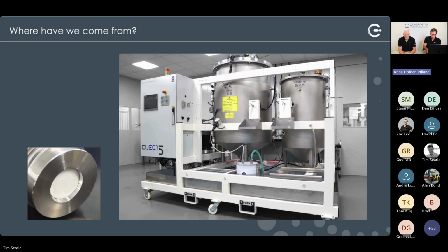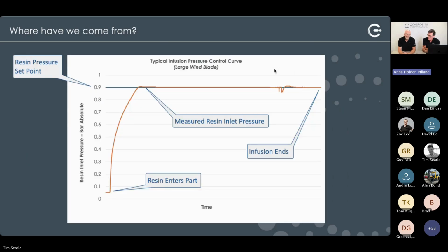And part of that journey was evolving the next generation of meter mix equipment, designed not just to mix and dispense materials, but to condition them carefully prior to the infusion, to infuse them directly into the tool with no intermediate stages, to get rid of buckets and hundreds of pipes, and to have extremely accurate control over pressure, flow rate, ratio, temperature, all whilst being able to feed on demand at fully variable flow rates ranging from almost zero right up to, for example, 30 kilos per minute. So verification and data collection really evolved during this sort of 2000s, 2010, 2020 period, and it led to very large data sets being created which we could analyze.